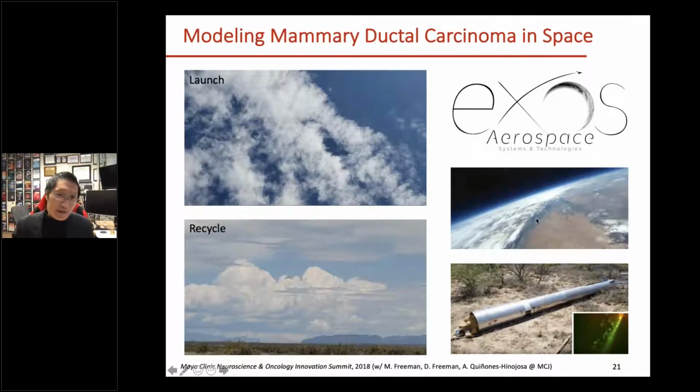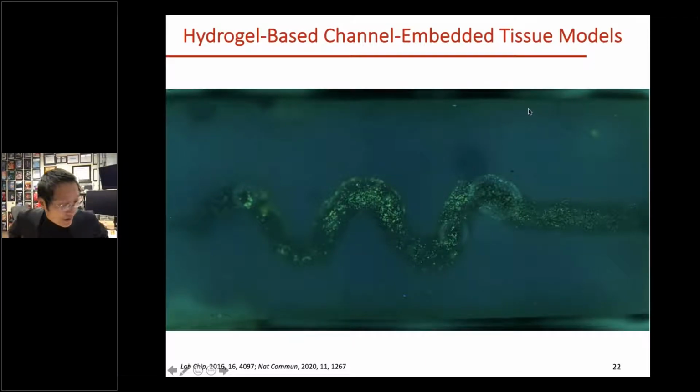All right, so coming back to the microchannels. We have been talking about these microchannels based on hydrogels, and they have been very instrumental in a lot of applications. But there are two potential issues. One is that these hydrogel matrices can be expensive, depending on which hydrogel you use. The second potential problem is that once you have made these hydrogels, you have to use them pretty much right away. They cannot really be stored because of their degradation profiles and other non-storable parameters.